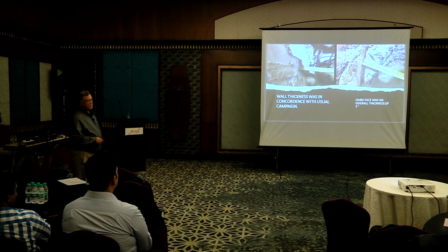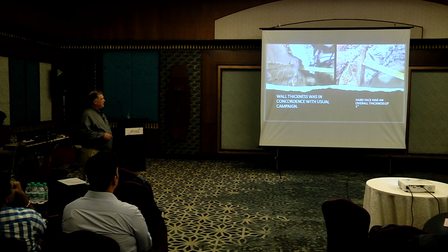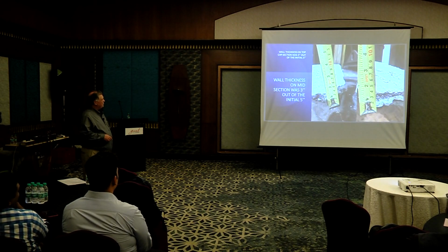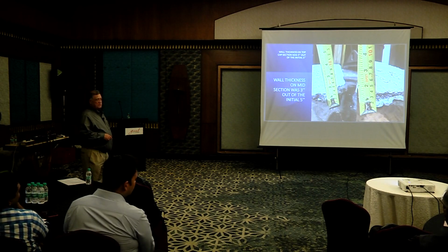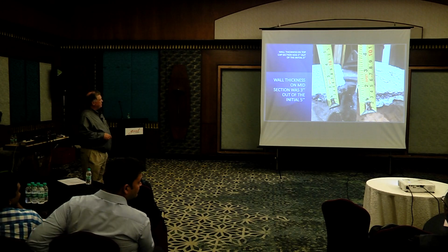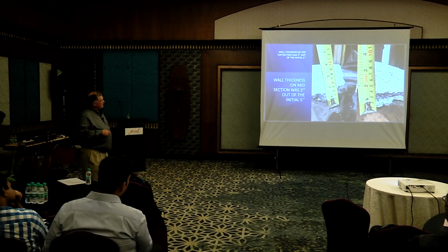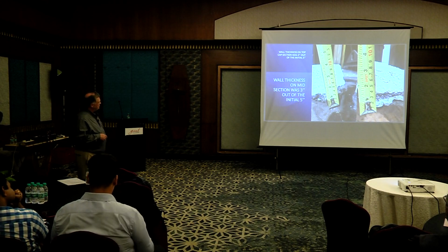In concordance with the usual campaign, there was no difference. They checked their lining every time they take it out. Hard face had an overall thickness of 1 inch. Wall thickness in the midsection was 3 inches. And you can see that we had a very good hot face formation, followed by a very good semi-sintered zone. So everything was good.